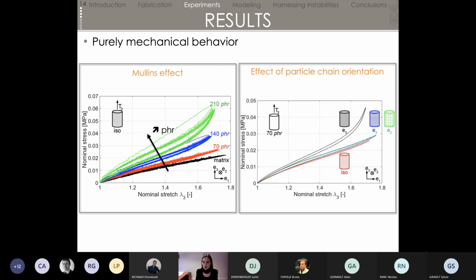Another effect that we could also notice was the effect of particle chain orientation. If you have an isotropic distribution of particles inside your sample, that gives you the softest response. Then for the two samples in blue and green, which have particle chains but perpendicular to the loading direction, we have the same response, so it's normal. And then the stiffest sample in the end is the one for which the chains of particles are aligned with the direction of the loading, which also makes sense because that's what you do when you reinforce concrete: you put the bars in the direction of the loading. So that's for the mechanical behavior.